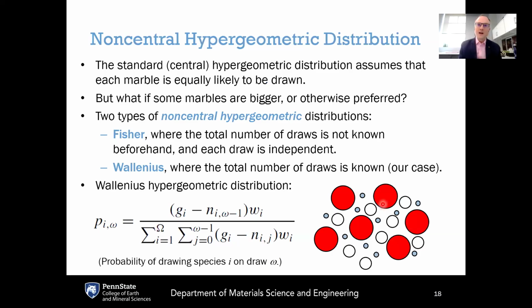Now, this is complicated by the fact that there's different energetics associated with those different possibilities. So, for example, even if you've got less alumina in the structure, alumina is more energetically favored to grab the sodium ions first because it is so unstable if it's in a non-tetrahedral configuration. So alumina will want to grab all the sodiums first to stabilize itself in a tetrahedral configuration. And so, for example, if the red marbles here represent aluminum, each aluminum ion here may actually be larger compared to the silicon or the boron atoms, where the larger size represents that it's more energetically favorable to draw one.